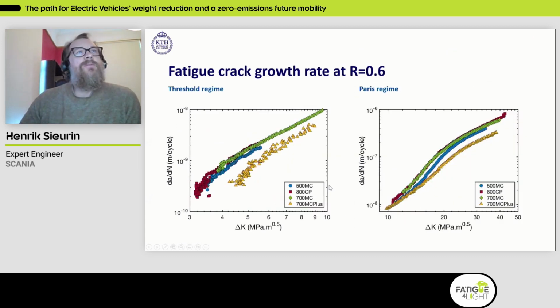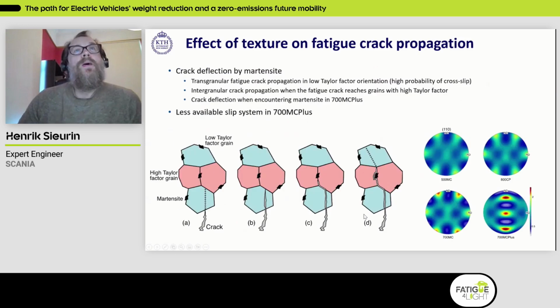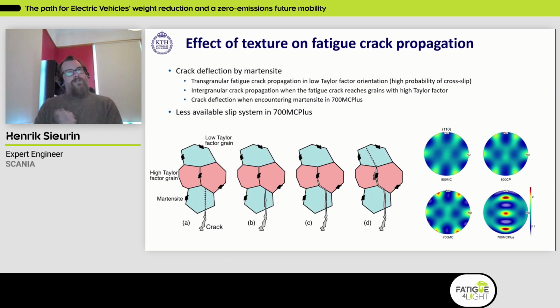And in his work, he found that this 700 MC plus material actually showed a much lower crack propagation rate compared to the other materials. And it also showed better fatigue properties, even in a punched hole compared to the other materials. And he has really dug deep into, studied how the crack propagates in the microstructures, and tried to describe these differences. And there are mainly 2 reasons that he has found.